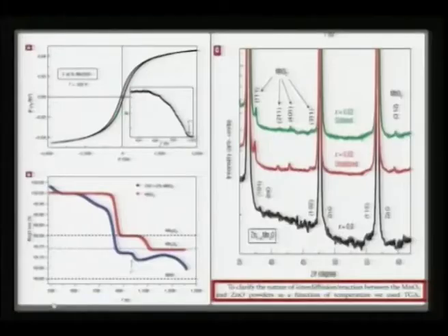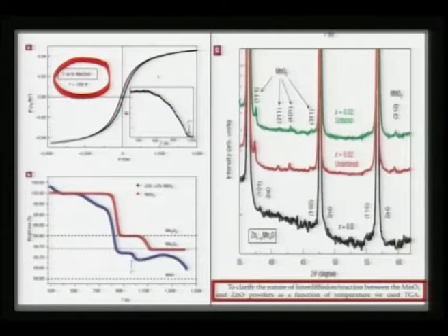Now this is the 2% manganese doped zinc oxide. If you measure, you will see a clear ferromagnetic loop, and that magnetic loop is at 300 K. Now if you look at this ferromagnetic loop, as clear as this, one would blindly say I have a magnetic material, and carefully if you try to run M versus T,